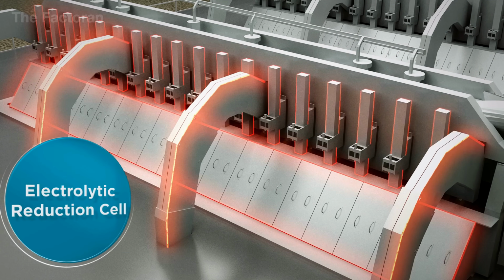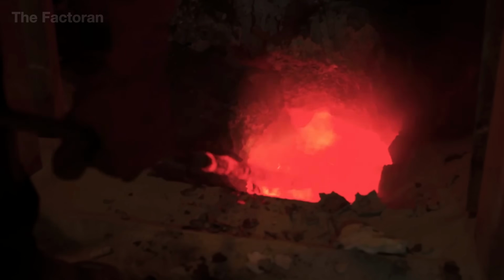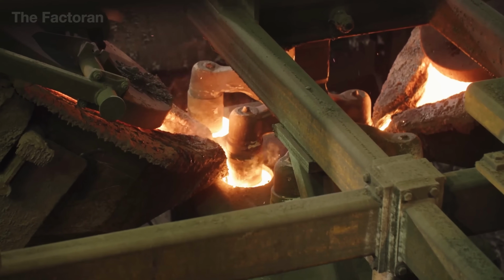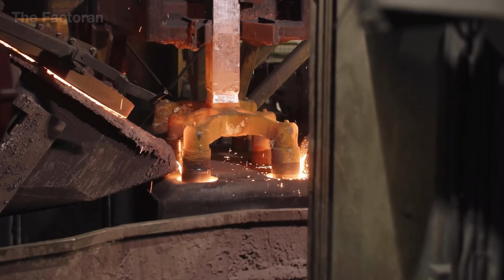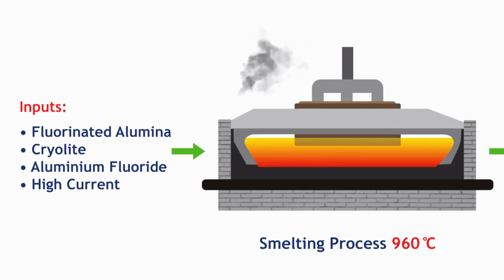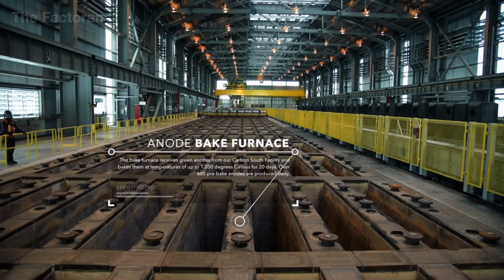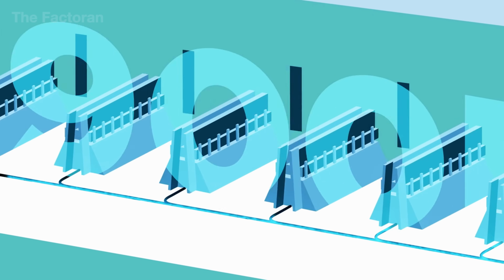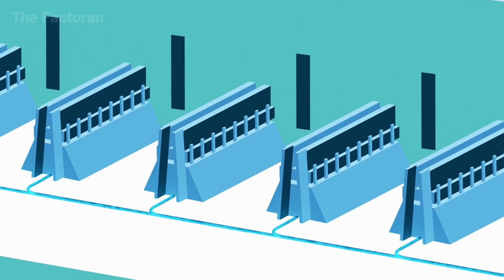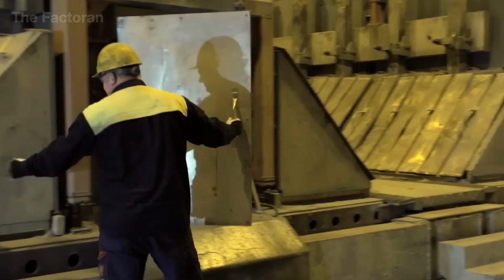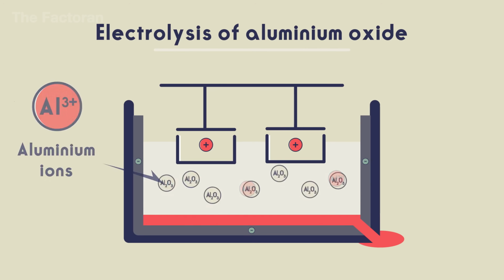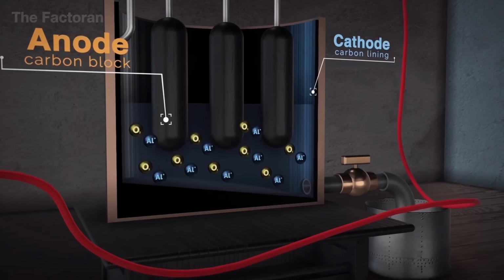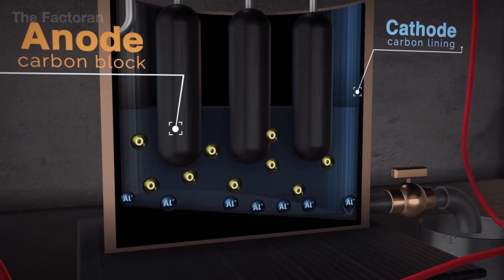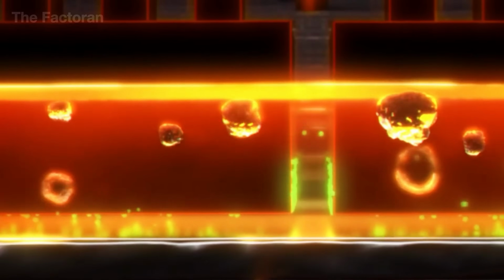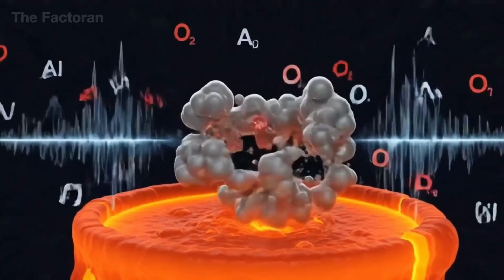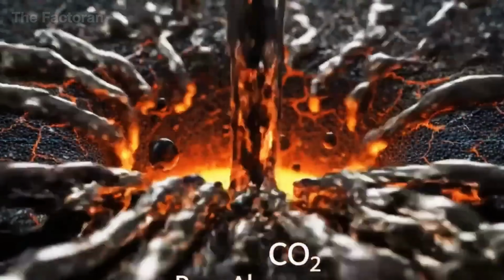After refining, the aluminum oxide is dissolved in molten cryolite and fed into massive electrolytic cells operating at temperatures between 1742 degrees Fahrenheit and 1832 degrees Fahrenheit. An immense direct current, on a plant-wide scale, 900 megawatts for the entire line, flows through the cells, breaking the bond between aluminum and oxygen. Molten aluminum settles at the bottom, while the oxygen reacts with carbon anodes to form CO2. These carbon blocks both conduct electricity and participate in the reaction, but gradually wear down and must be replaced periodically.